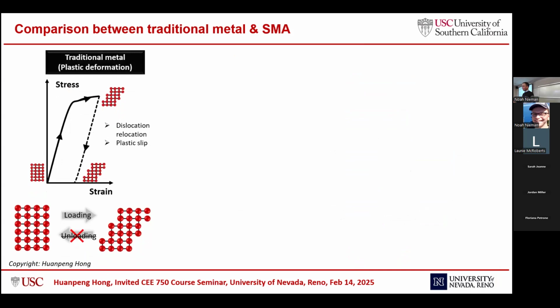So here's what happens at the stress-strain level and the microstructural level. For traditional metals, after yielding, if we keep loading it, dislocation, relocation, and plastic slip are all irrecoverable. And if we unload it, it will end up with some permanent deformation, a residual strain. That means after unloading, the plastic deformation is not recoverable.